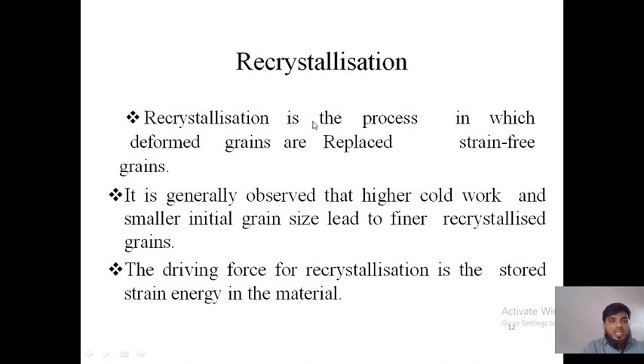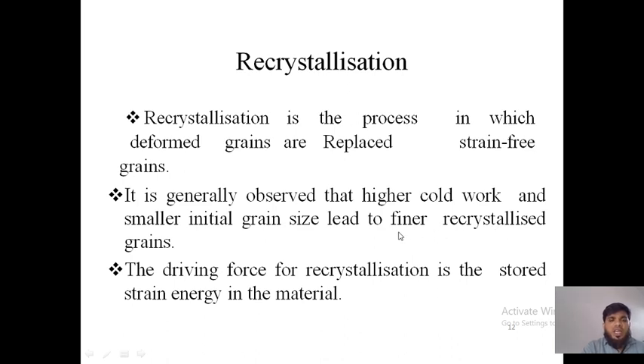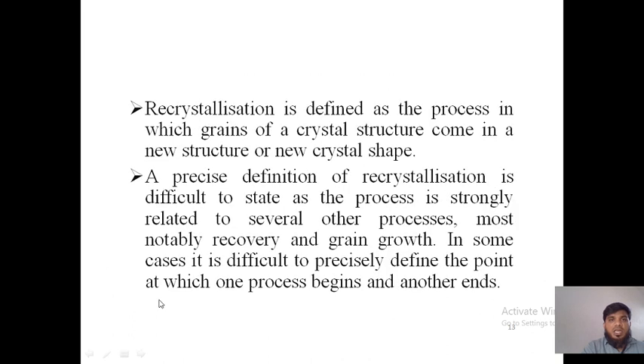Recrystallization requires annealing beyond 0.5 of the melting temperature. It is a process in which deformed grains are replaced by strain-free grains. High cold working and smaller initial grain size lead to finer recrystallization. If the crystal structure has small grains initially and annealing is done beyond 0.5 melting temperature, finer recrystallization results, increasing strength. The driving force for recrystallization is the strain energy of the material.